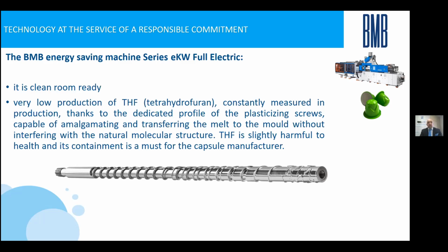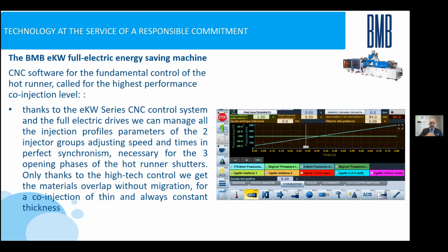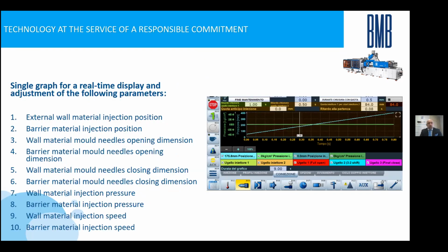The screw, for sure, has an important responsibility on it, and we control the process. The controller is very important in this case because there is a co-injection between 2 materials. In only one page, you can see all data necessary to manage, control all information concerning the 2 injection units. Here you can see what we control in one page, because the really important matter to produce this type of